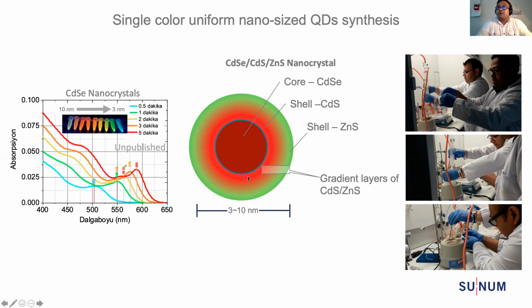So what we did was, in order to get uniform single color crystals, we had to have these quantum dots made of core, while the shells, thin layers of shells, should be formed in a gradient way. There is no clear-cut demarcation between the cadmium selenide layer right on top of the core and the outermost layer made of zinc sulfide. So this was very interesting to us. We were successful in making it.